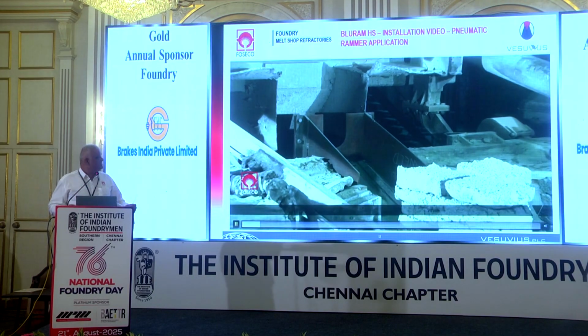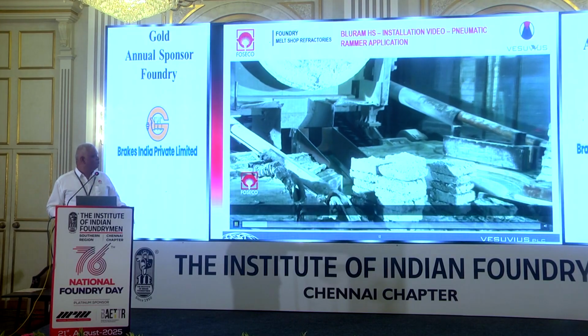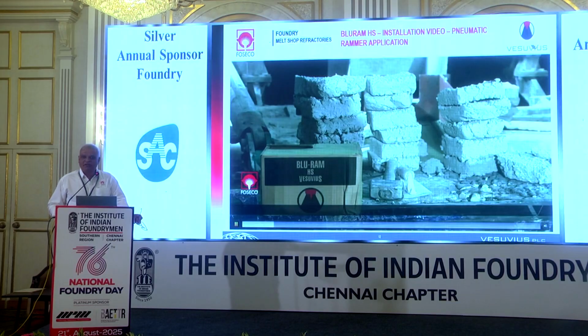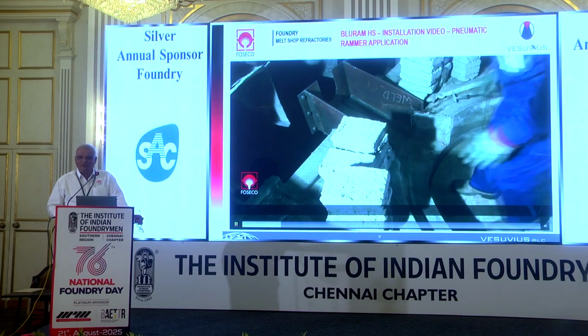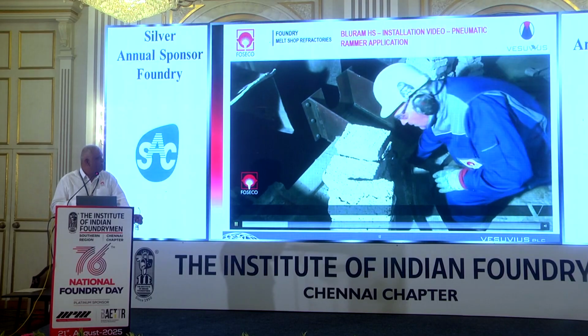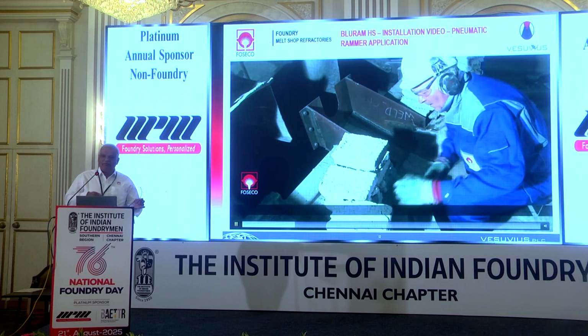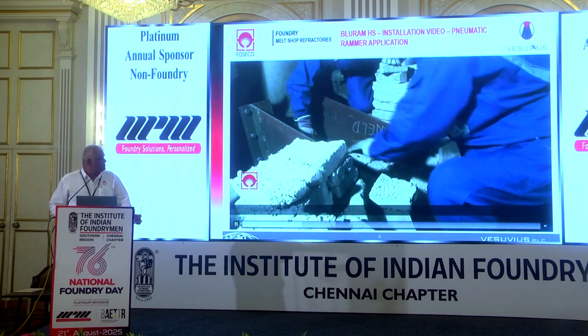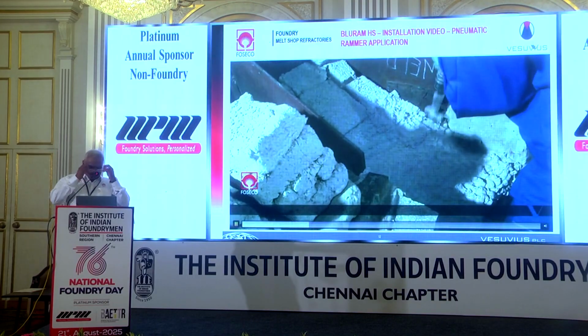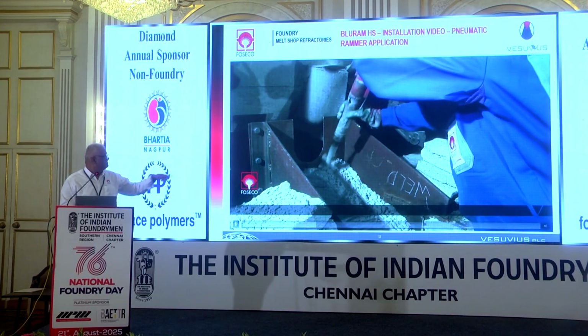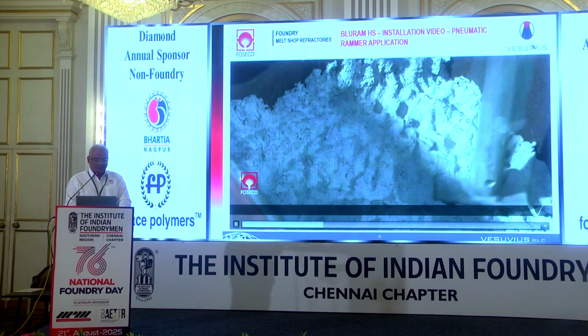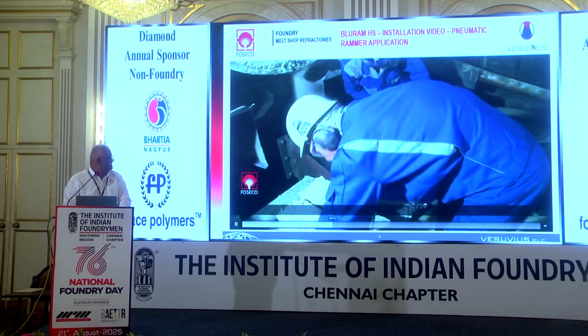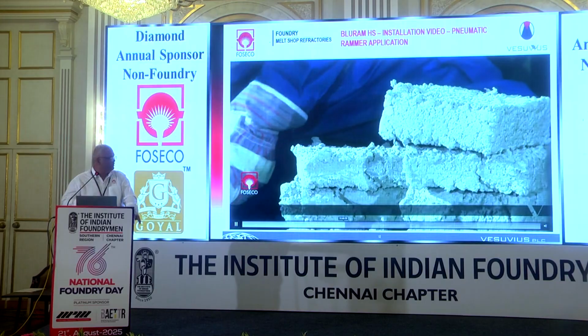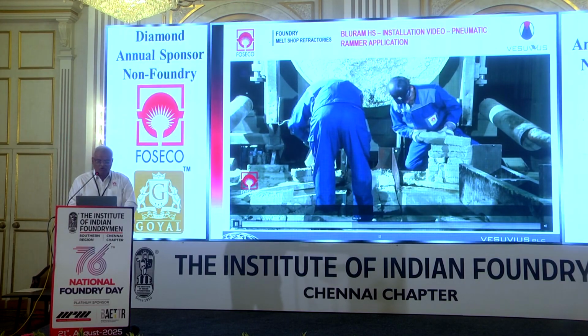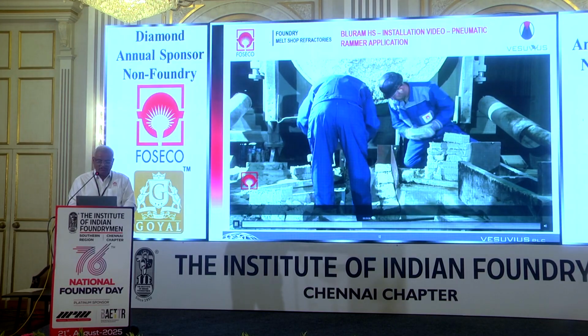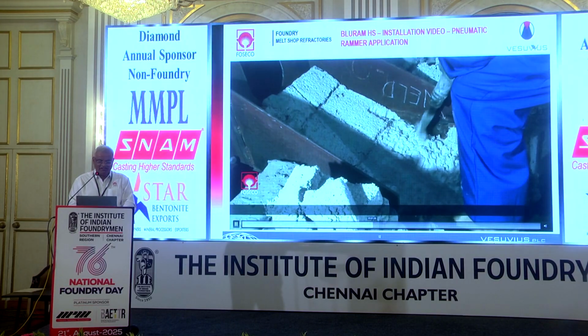So this material comes in cake form. To get a better idea, we have taken a video of a big furnace, and the furnace size is around 15 metric tons. So here you can see how it can be applied. This cake can be used with vibrators. It can be settled out. As we are running out of time, I will just fast forward this. So here with this vibrator, they are ramming that material. Then they can add some blocks on that. Similarly, they can do the ramming. Then for the spout, from where metal is to be transferred, they can put a former there and get that shape.